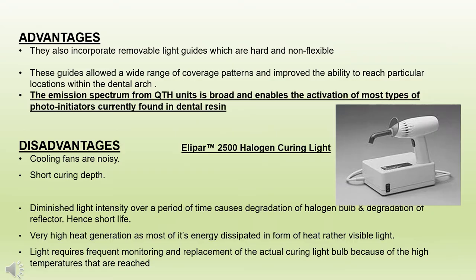The advantage of this unit is that the emission spectrum from the QTH units is broad and enables the activation of most types of photoinitiators currently found in dental resin. The disadvantages of these units are short curing depth, gradual loss of high energy wavelengths in their light output, and very high heat generation, as most of its energy is dissipated in the form of heat rather than visible light. They only use 9% of the total energy produced, and the majority of it is dissipated as heat and so requires a cooling fan and filter.